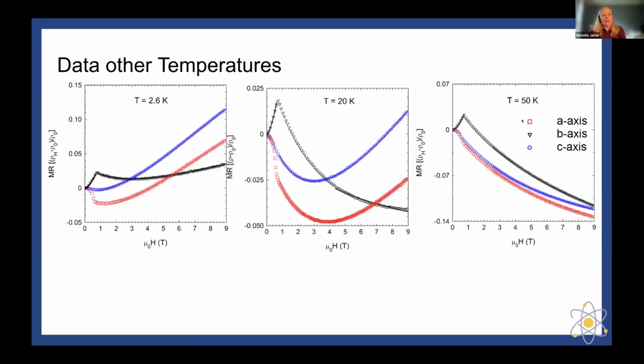So what we see is that, compared to the 2.6 Kelvin data that I just first showed you, where we see this huge increase of the magnetoresistance along the B axis, after the critical field for the spin flop transition, it starts to behave kind of like a normal metal. Whenever we get up to 20 Kelvin, where we're still in that ferromagnetic state, we still see that big increase. And then we start to see more negative magnetoresistance, indicating that, hey, it looks like a metal.